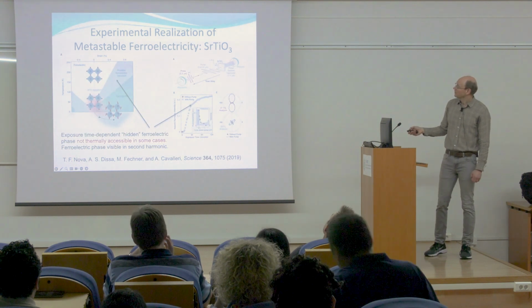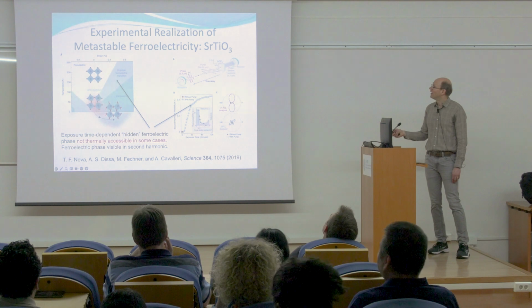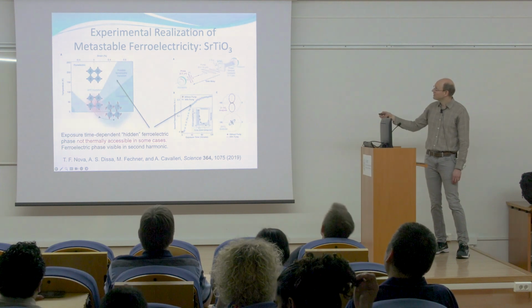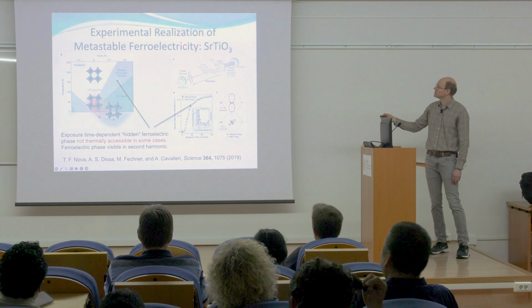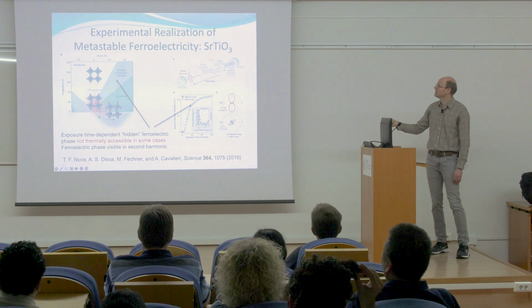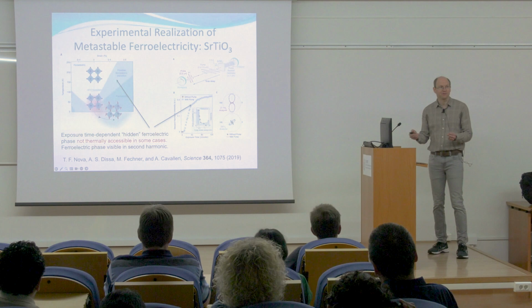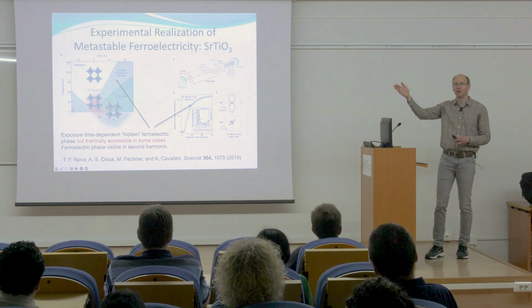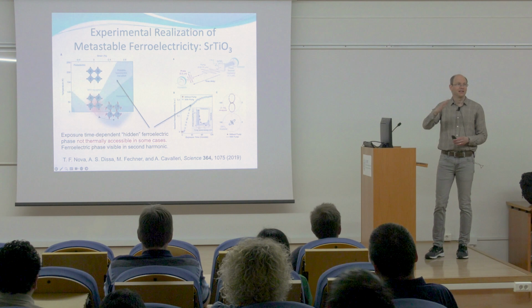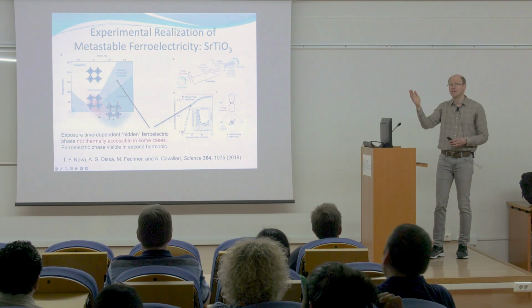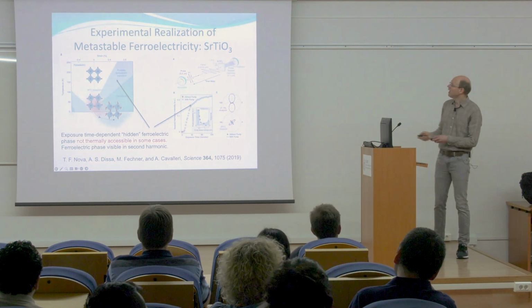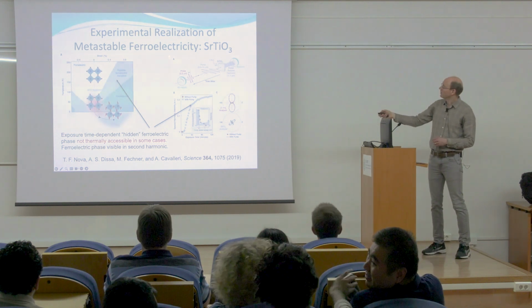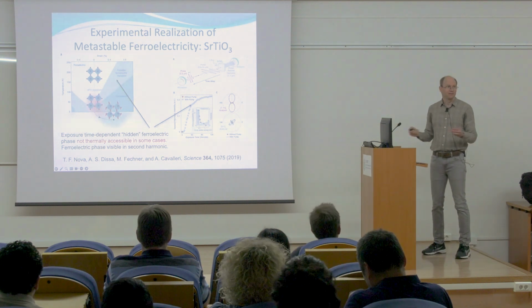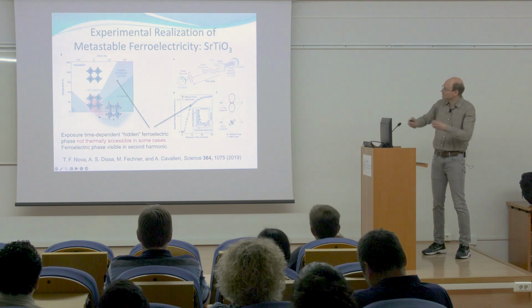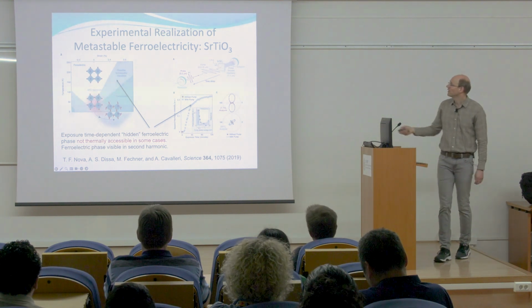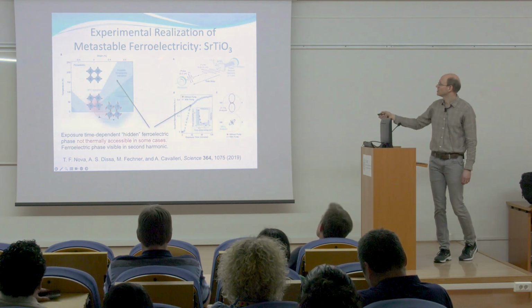And so kind of a final example in this category is this strontium titanate. So this is a material which has an order called ferroelectricity. So it's kind of like ferromagnetism. So ferromagnetism is the alignment of magnetic moments. Ferroelectricity is the alignment of charged dipoles. And so this material is only ferroelectric if you apply a strain on the system. So you have to stretch the lattice in some particular way, then it will undergo this ferroelectric transition.